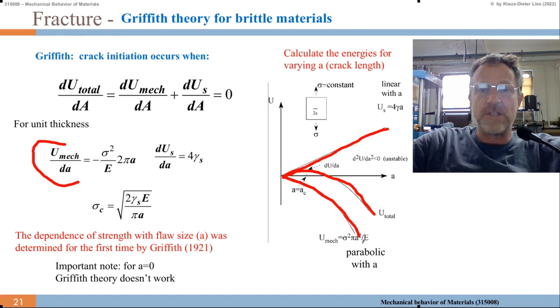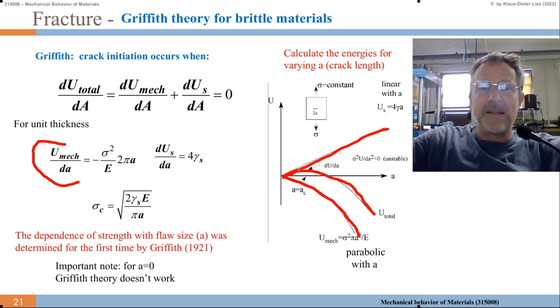And when I put the two together, the slope of the down curve is not as steep as the slope of the up curve at A equals 0. So the tangent here means it first increases with the upper curve, but then the slope of the second curve becomes steeper, so then it goes down, and I get a position A critical where dU over dA becomes 0.